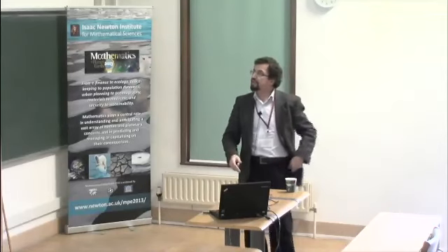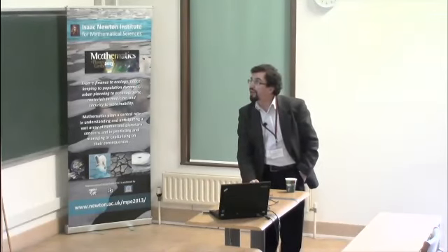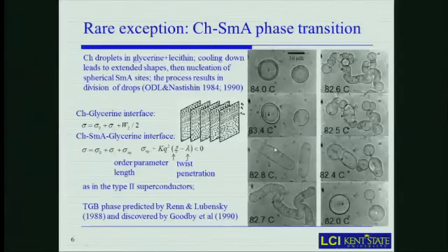It was to us as if the surface tension became negative or close to 0, and then the smectic phase nucleated at the sharp ends of these elongated forms, and the smectic phase, of course, by itself wants to form round pieces of the liquid crystal, and since they form at different locations, you have a dynamics that breaks the original droplets and produces smaller droplets in the system.